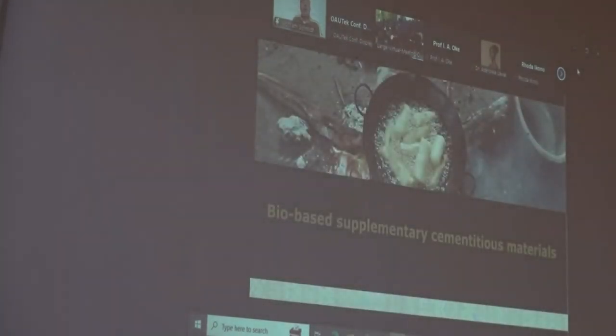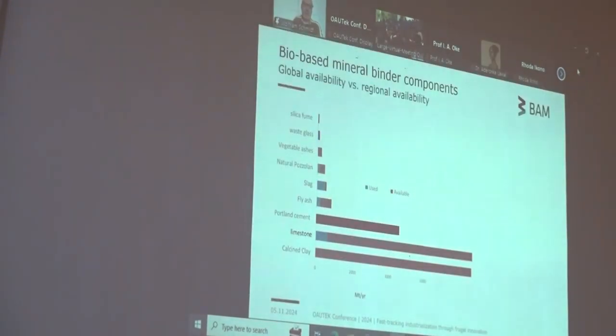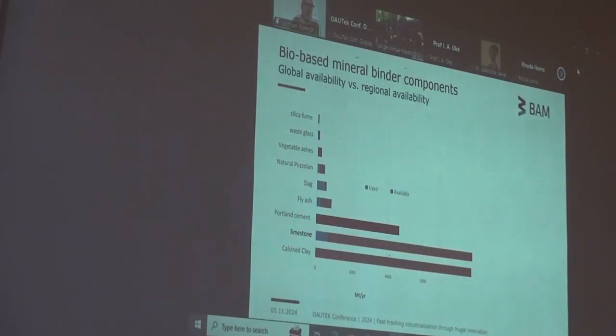And then we do not only have organic admixtures that just give a slightly better consistency, but we can also replace cement by bio-based resources. And typically people rubbish this idea. So this is a figure which is often shown in presentations where people say, okay, this is the amount of Portland cement which we have to replace, and this is the amount of vegetable ashes that would be theoretically available. And since this is so small in comparison to the Portland cement, people say this doesn't make sense.